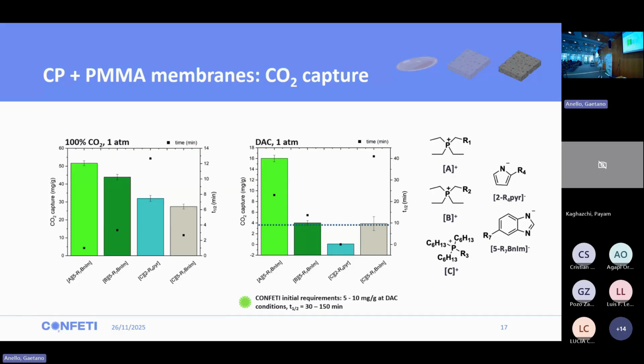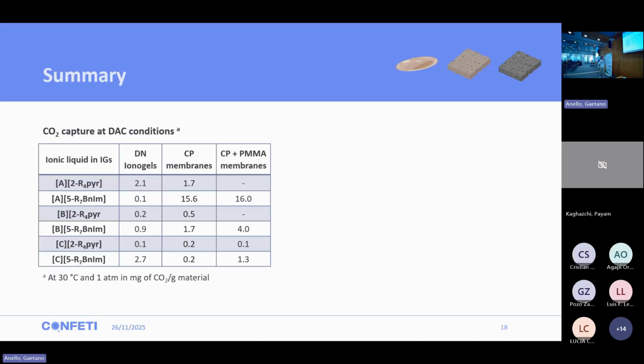For the other 4 materials, we obtained similar results to the previous one, the carbon paper one, and also in the DAC conditions, where we achieved a maximum of 16 milligrams per gram. But the important thing of these materials is that with this polymer lipid system, we can avoid the ionic liquid leakage. So just as a summary, here I put all the materials that we developed, the 3 different types of materials with the 6 ionic liquids, and we can see that we achieved 2 different materials with higher captures at DAC, that meets our requirements.